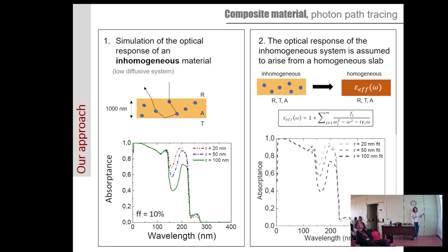So how do we do it? Basically, we consider a 1 micron film thickness of silica with polystyrene inclusions of 10%, for instance, and we change the radius of our system, and we compute the absorption of our system. Okay. And now we say, okay, how would be the permittivity of a system that is homogeneous and gives me this response? Is it clear? So I send all my photons and do all the things, and then I have these properties where I'm taking into account my theory and so on. And now I say, okay, I want to know with a genetic algorithm, if I have just a homogeneous system with this response, how is the effective permittivity there? And this is what we did. This is our fitting.